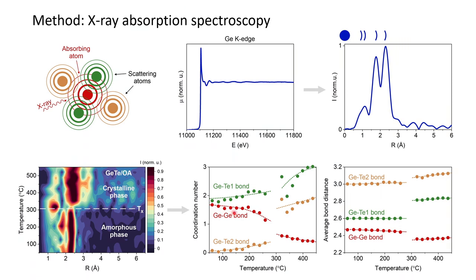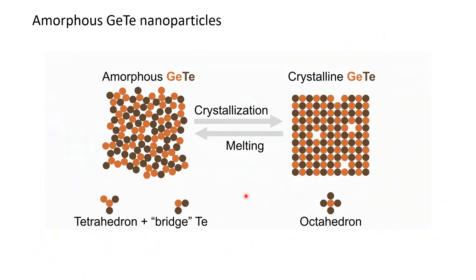Which means some of the atoms in the germanium telluride structure would switch their positions, and this will give us a germanium-germanium bond. What's convenient in this case is that the amount of germanium-germanium and germanium-tellurium bonds is about the same. So we looked in the literature and did the following thought experiment. We do it in 2 dimensions first. So for crystalline, again, one expects to have octahedrons. So this would be this shape. And then you can fill the space regularly just using this octahedron.